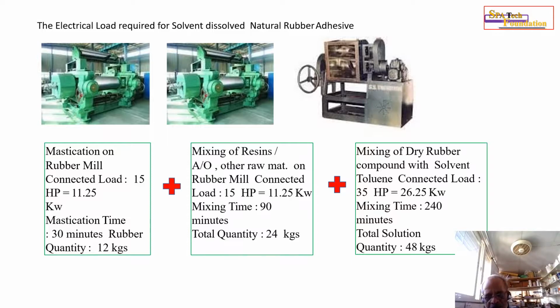Mixing of dry rubber compound with solvent, toluene or petrol or hexane. The connected load is 35 HP, that is equal to 26.25 kW or units. Mixing time is 240 minutes. Total solution capability of the sigma is 48 kg.